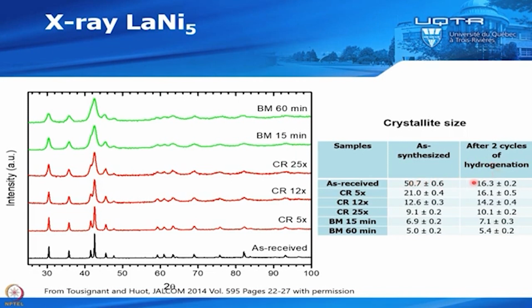So you see that even for the as received, the crystallite size will reduce in this case because of the decrepitation of your material. But you see here, you go from 21 to 16. So you have a reduction, but here you have an increase, okay? And here it's more or less constant, but it doesn't absorb hydrogen so much. But so you see that it looks like you have a natural size of crystallite. After cycling, it will tend to have a certain size of crystallite.